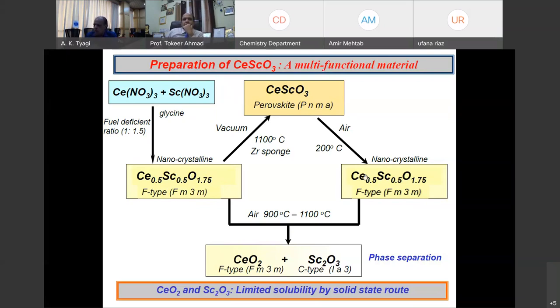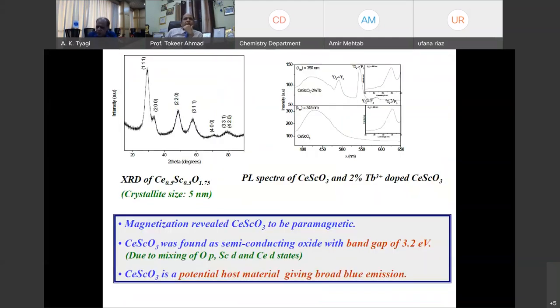These kinds of compounds are very important for applications. I'll give some more examples. So this compound, of course, magnetism wise, was only paramagnetic. Band gap was 3.2 eV. And the compound shows a beautiful blue emission. You dope some terbium, you get blue emission coupled with green emission. The compound shows multifunctional properties.